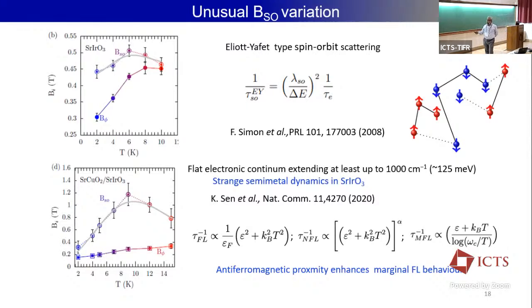But we came across a paper based on Raman spectroscopy studies, and they found that SrIrO3 is a strange semi-metal. It has strange semi-metal dynamics. They found that the electronic continuum extends even up to 1000 centimeter inverse, roughly 125 milli-electron volt, very similar to some of the parent compounds of high Tc superconductivity. So, there are some of these cuprates.